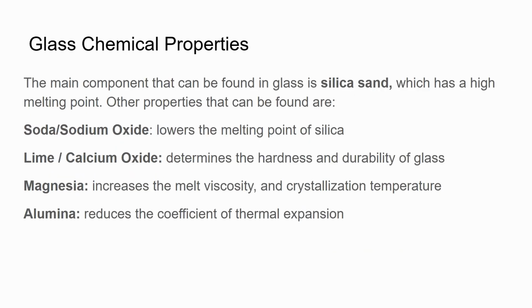Beginning with chemical properties, the main component found in glass is silica sand, which has a high melting point. Other components found in glass are soda, or sodium oxide, which lowers the melting point of silica; lime, or calcium oxide, which determines the hardness and durability of the glass; magnesia, which increases the melt velocity, viscosity, and crystallization temperature; and alumina, which reduces the coefficient of thermal expansion.